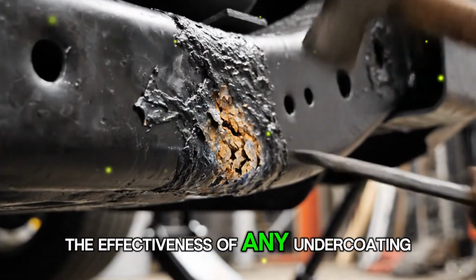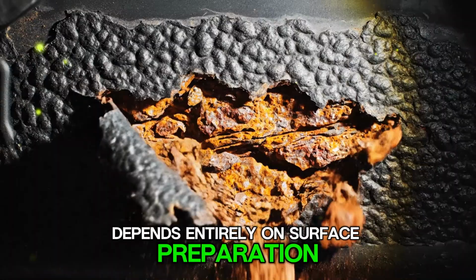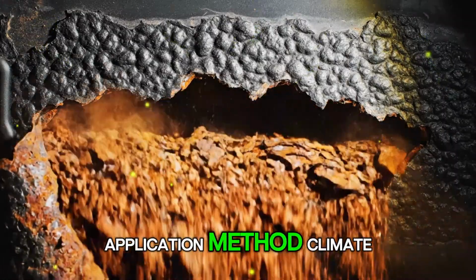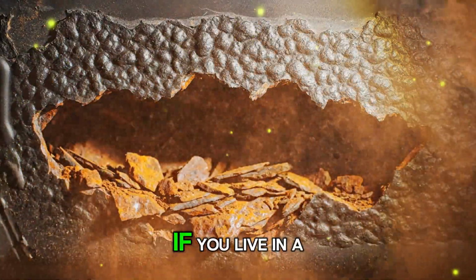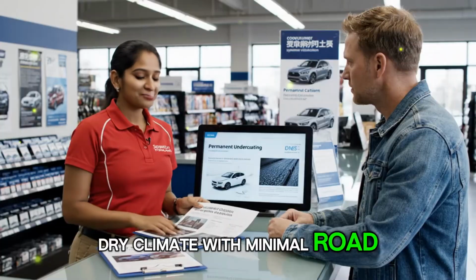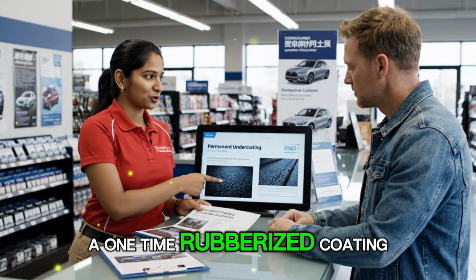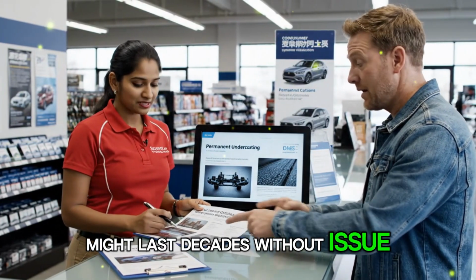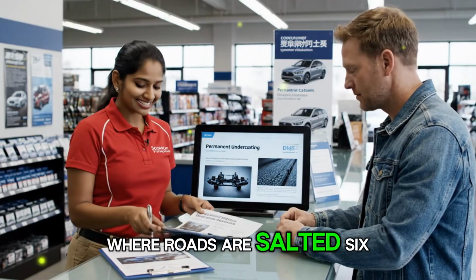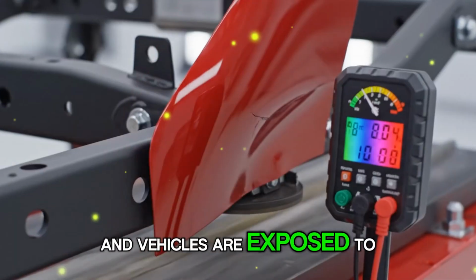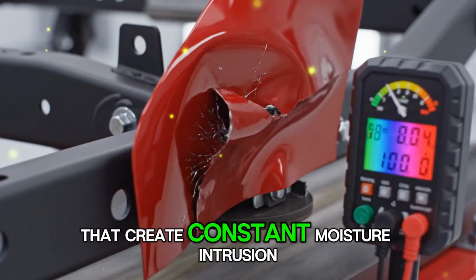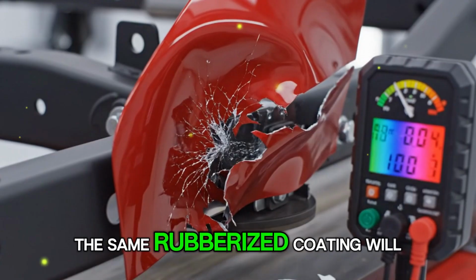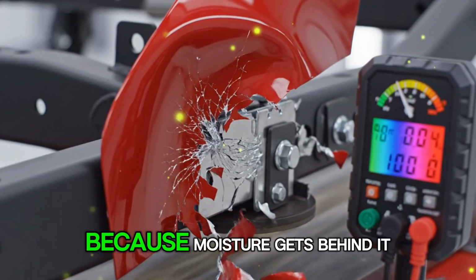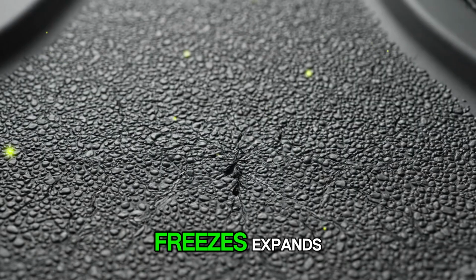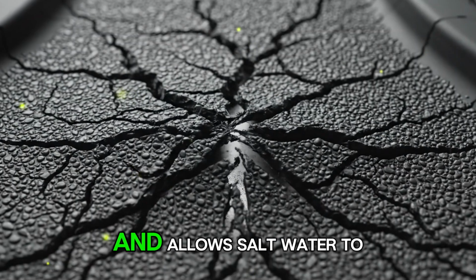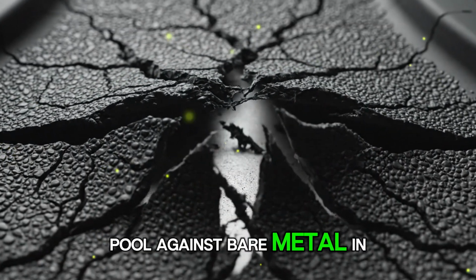The effectiveness of any undercoating depends entirely on surface preparation, application method, climate, and maintenance schedule. If you live in a dry climate with minimal road salt exposure, a one-time rubberized coating might last decades without issue. If you live in the Rust Belt where roads are salted 6 months a year and vehicles are exposed to freeze-thaw cycles that create constant moisture intrusion, that same rubberized coating will fail catastrophically because moisture gets behind it, freezes, expands, cracks the coating, and allows salt water to pool against bare metal in a sealed pocket.